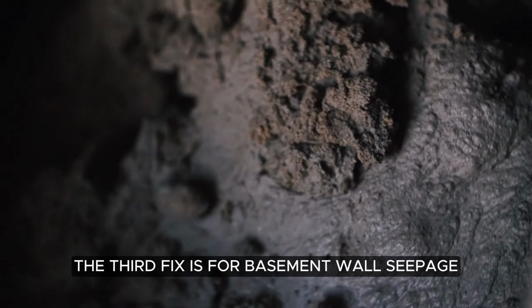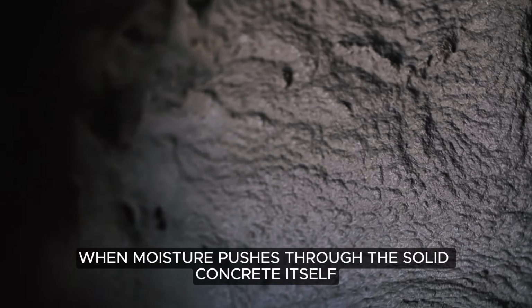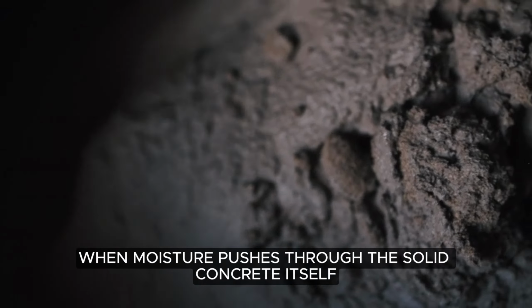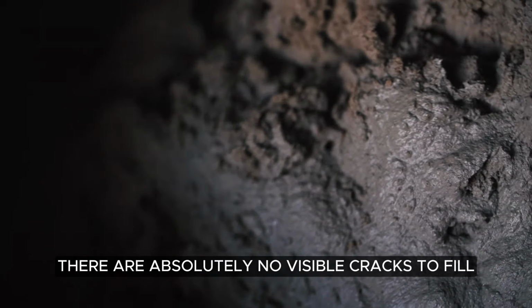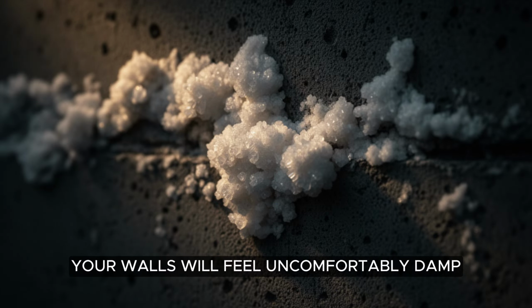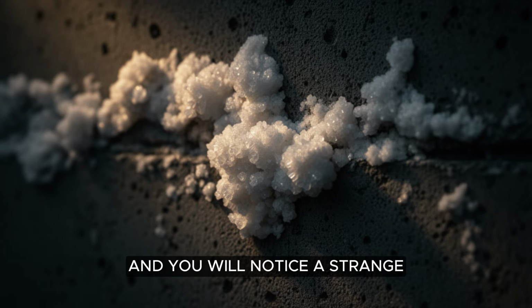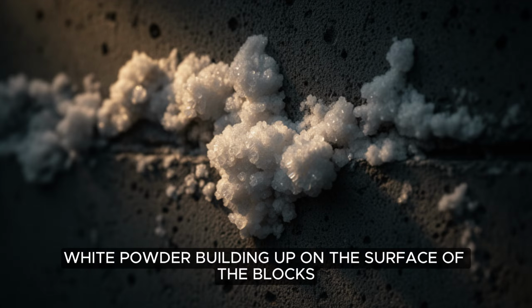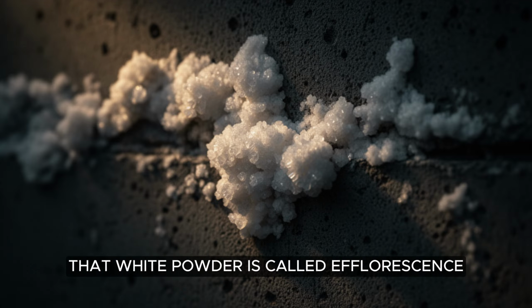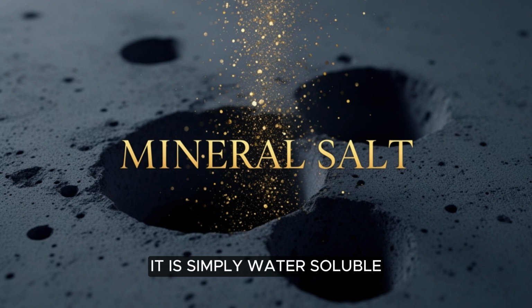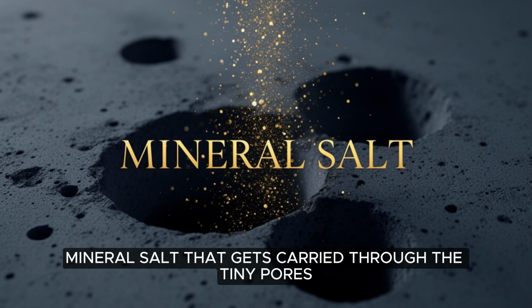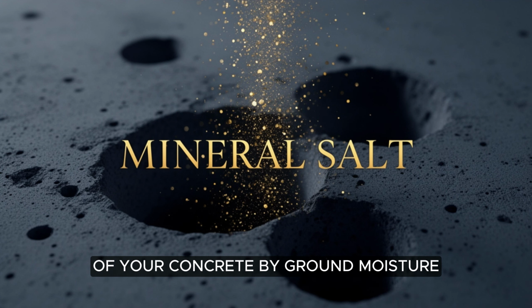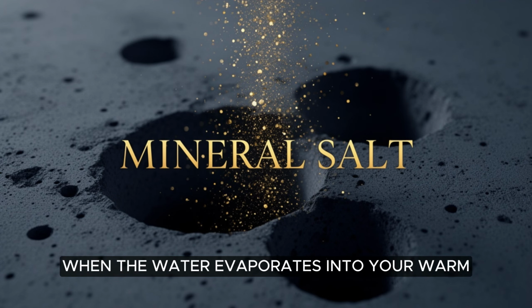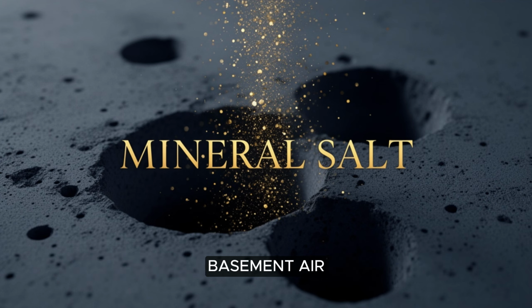The third fix is for basement wall seepage, which is when moisture pushes through the solid concrete itself even when there are absolutely no visible cracks to fill. Your walls will feel uncomfortably damp, and you will notice a strange, crusty white powder building up on the surface of the blocks. That white powder is called efflorescence. It is simply water-soluble mineral salt that gets carried through the tiny pores of your concrete by ground moisture and is left behind when the water evaporates into your warm basement air.